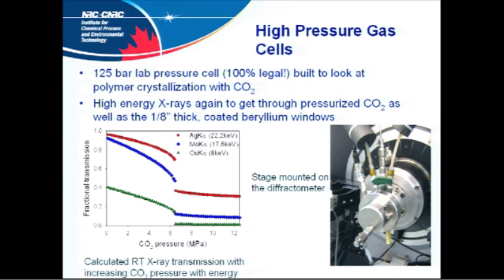And here you can actually see, in terms of a theoretical calculation, what your fractional transmission is with CO2 pressure with the different energies. And you can see here that if you used copper radiation with this, you start not too bad and it steadily gets worse. And all of a sudden your CO2 liquefies, bang. Basically you get nothing at all.